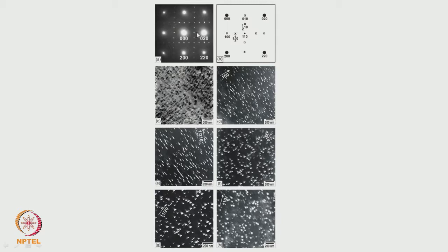What I have done is gone to two beam condition, put an aperture around the central spot and imaged it. That is where I get this bright field picture. Then I have taken this reflection, put an aperture around it and imaged it in the dark field. I get some ellipsoidal shaped second phase particles that could be seen.